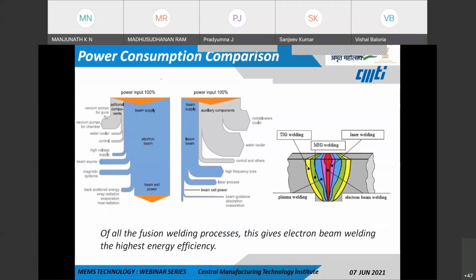So here is a graph which shows the power consumption comparison between laser welding and e-beam welding. When we see the 100% power input, most of the power, almost 80%, is being consumed by the auxiliary components such as water coolers, controls, high frequency tubes, and laser processors, and the beam exit power. So finally, the beam exit power is almost only 10% of the input power. On the contrary, in electron beam welding, out of the 100% of the power, almost 80% of the power is used for welding. So of all the fusion welding processes, electron beam welding gives the highest energy efficiency.